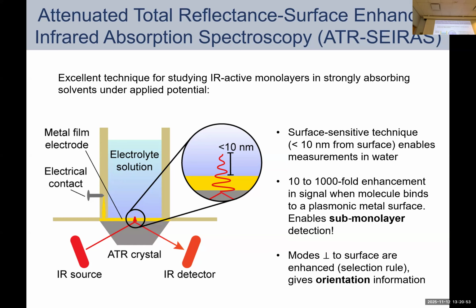And we're going to now take advantage of the fact that SEIRAS is surface sensitive, meaning that we're going to be selectively probing signals that come from molecules that are adsorbed at the surface rather than existing just near the surface in solution. It's not perfect, so you absolutely still can see some signatures from molecules that are not actually adsorbed to the electrode, but you have much better enhancement of molecules that are actually chemisorbed. Okay, I'll talk about a little bit more detail in a second.